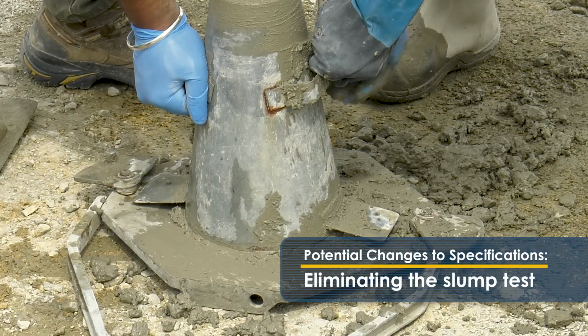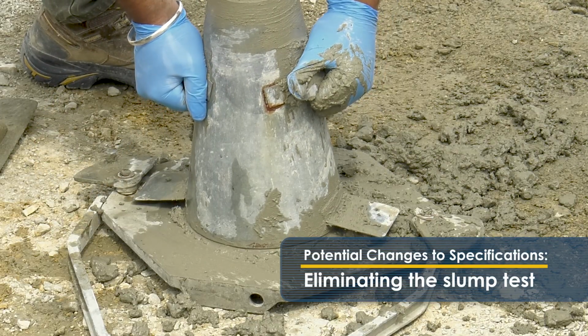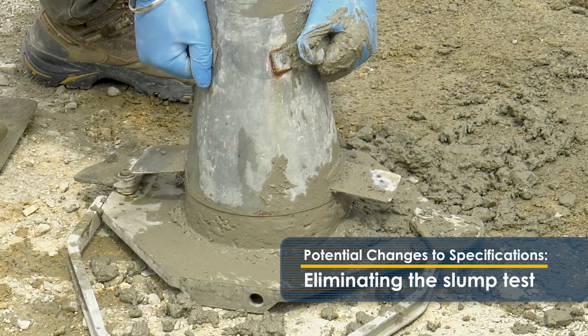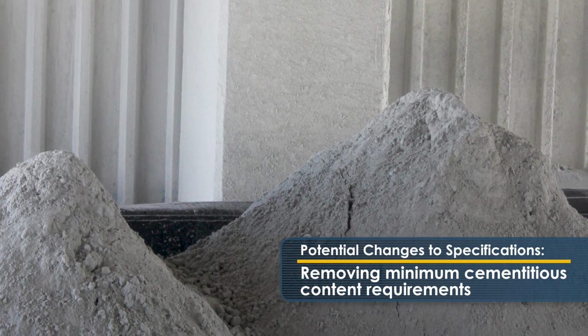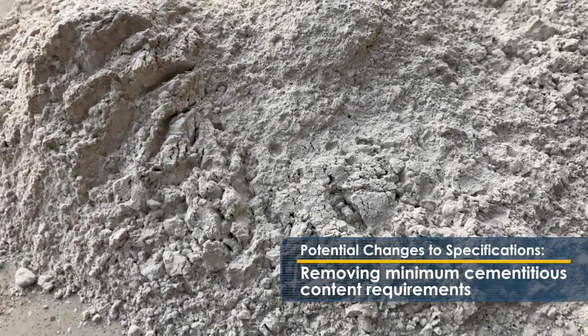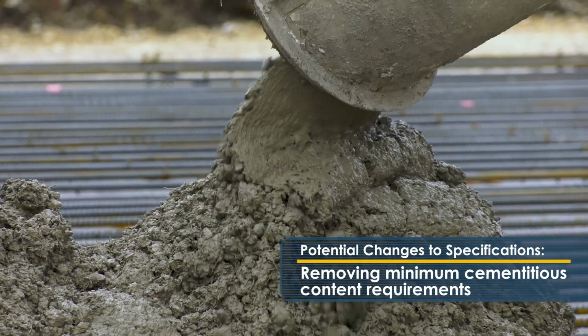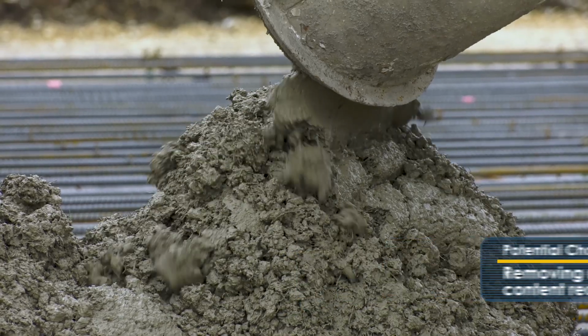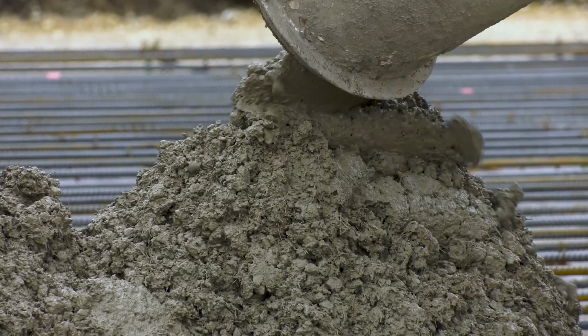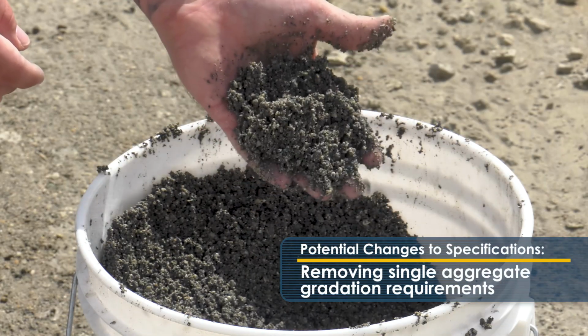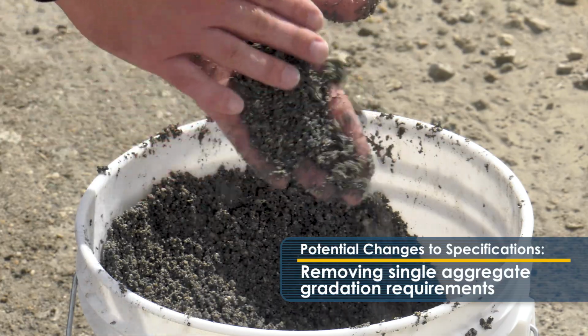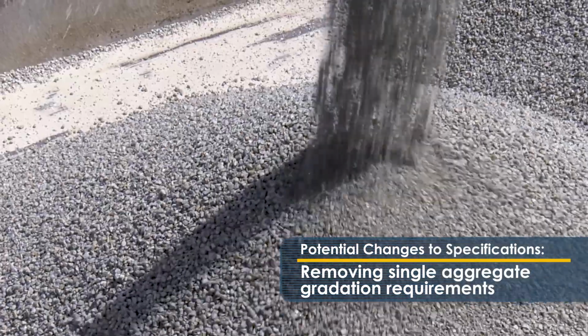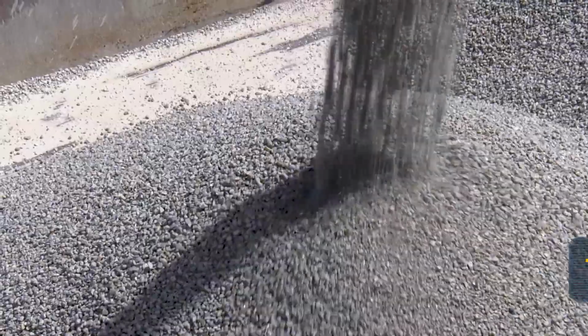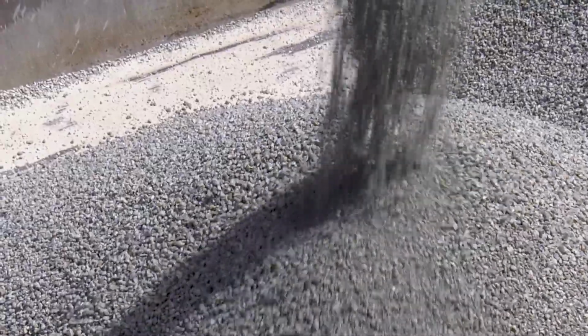Examples of potential changes to specifications include eliminating the slump test because it does not correlate to durability, removing minimum cementitious content requirements, and relying on the contractor to proportion and design the mixture to meet agency testing requirements. Removing single aggregate gradation requirements because gradation of the aggregate blend rather than that of a single aggregate is the key factor that impacts performance.